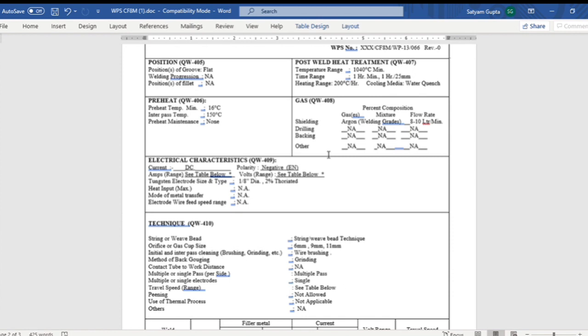Then the second point is the interpass temperature. Interpass temperature is defined as 150 degrees, which is the maximum temperature. So for each welding pass, we need to check the temperature of the bead, and it shall not be more than 150 degrees. Then in this I have taken one example where PWHT temperature and time range is mentioned. So we need to perform PWHT after performing the welding as per QW407. Okay, now in QW408 we define the gas. We have to use argon gas because this is a GTAW welding process. The flow rate will be 8 to 10 liters per minute.